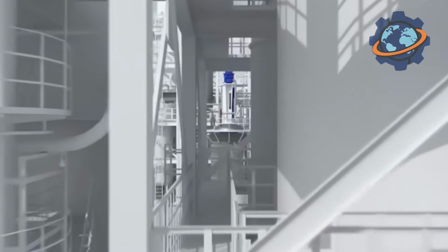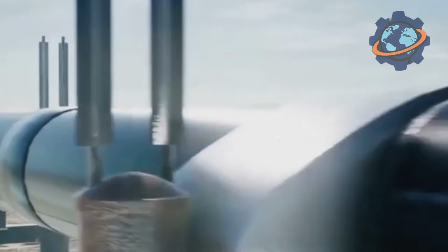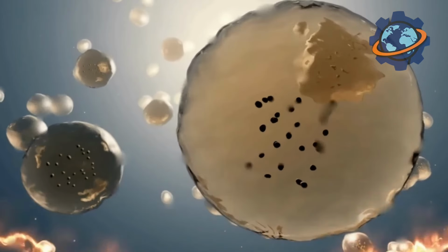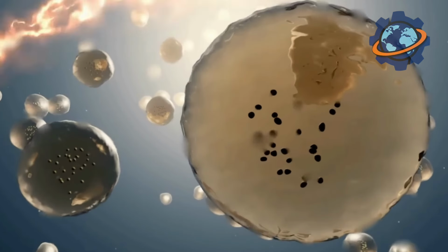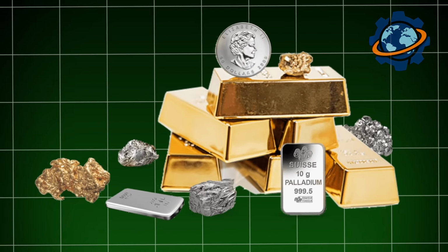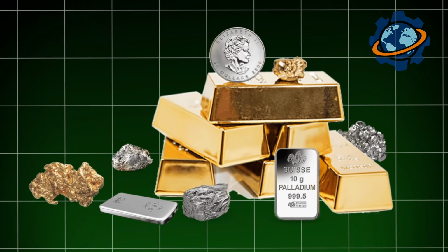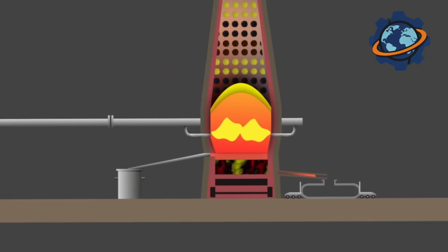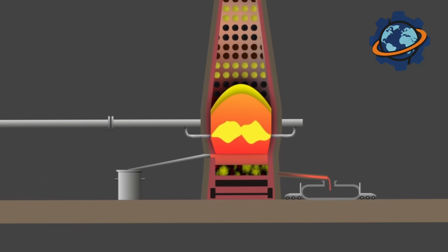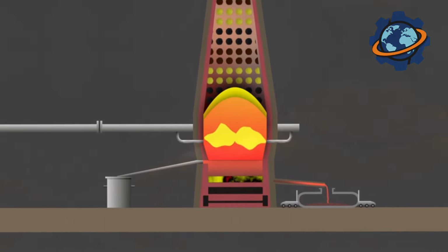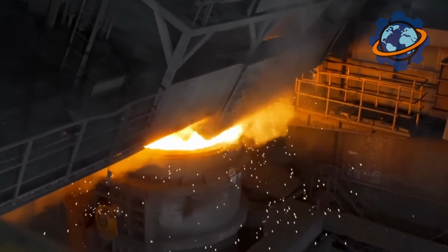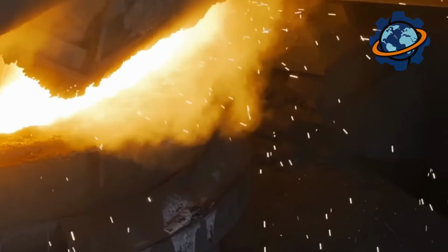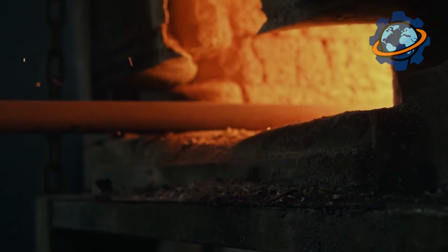Picture this: over 10 days, nickel migrates atom by atom across 6-inch gaps. Impurities like cobalt, copper, iron stay behind, falling as sludge to cell bottoms. This sludge, later processed separately, contains precious metals including platinum, gold, palladium, making waste worth more than many ores. Temperature control matters critically. Too hot, dendrites form, metal crystals bridging electrodes causing shorts. Too cold, deposition slows uneconomically.